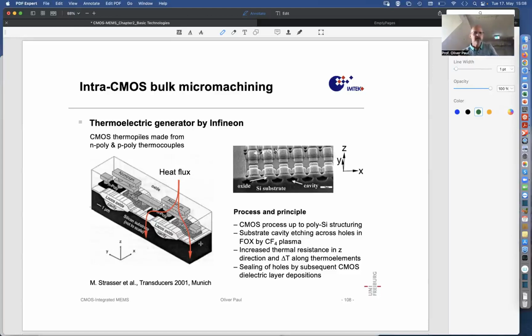Once this is done, the oxide bridges are covered by polysilicon, and that's the polysilicon of the circuit. They have some N and some P polysilicon here. It's a double poly process. These structures of N and P polysilicon are partially sitting on that oxide bridge, thermally insulated from the cavity, and of course electrically insulated. Then such elements can be connected electrically by the aluminum of the CMOS process in series. So when you look at this, you see immediately a thermopile. Any of these elements is a thermocouple.